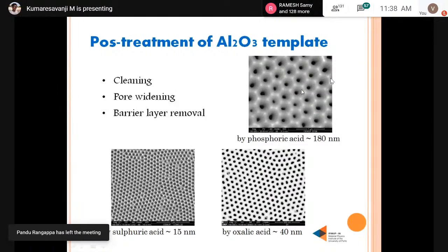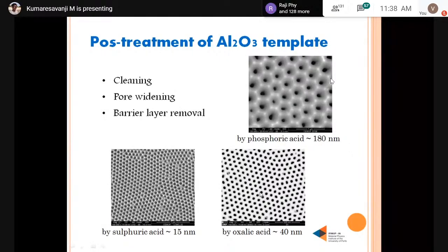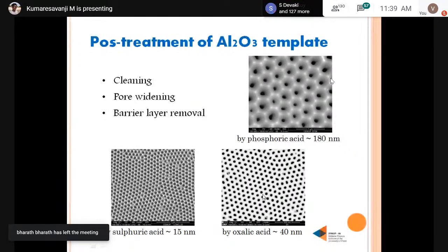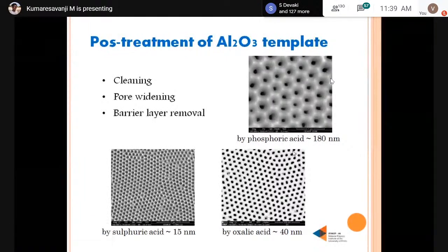This template is prepared by phosphoric acid, where the nanopore is about 180 nanometers. Here it is prepared by sulfuric acid. The nanopore is about 15 nanometers. This is prepared by oxalic acid. It's about 40 nanometers. So you don't need to think that it is only 15, 40 or 180. We can enlarge this pore size also. If I want to get 60 nanometers, I can do the pore widening by some chemicals. With the chemical etching method, I can widen the pores. So I can get 60 or 70 or 50 nanometers, or 20 or 30 nanometers, or in this case I can get 200 or 210. Also the barrier layer can be removed by chemical etching.